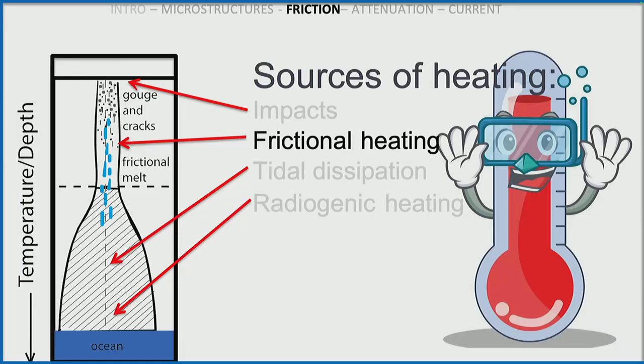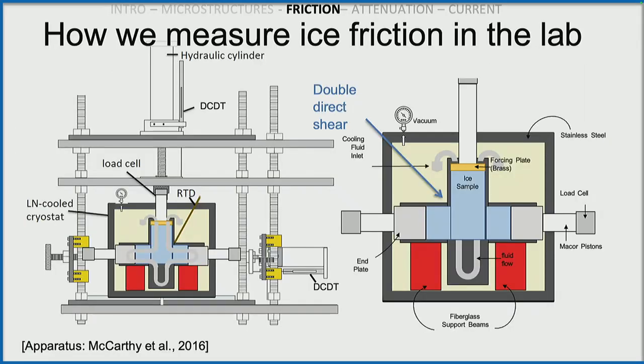Okay, so let's start with frictional heating friction experiments. How do we run a friction experiment? We have a cryogenic biaxial apparatus that is very similar to what Damien's lab has, Chaz's lab has. Essentially, you've got to squeeze two pieces together and slide them past one another, right? Ours is a double direct shear, which in the horizontal direction squeezes our 3 blocks together, and then we use the vertical piston to slide the central block past. So we're measuring the normal stress that we're applying and the shear stress of these two interfaces, measured with a load cell up here, where friction is shear divided by normal.